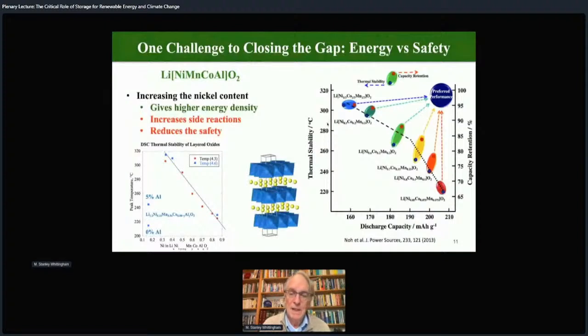So initially in these layered oxides, there were equal amounts of nickel, manganese, and cobalt. That's shown up here. This has the highest thermal stability. So all these layered oxides are metastable. If you heat them up after they've been charged, they will evolve oxygen. This oxygen then is an internal source to burn the battery. So we'll have to be very careful. So this is the safest one, but its capacity is only 160. If you go to more than 80% nickel, you can get well over 200, but then its thermal stability is 100 degrees lower. So there's this trade-off between energy and safety.